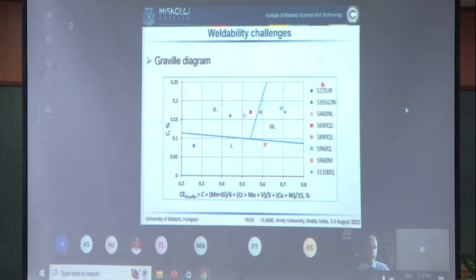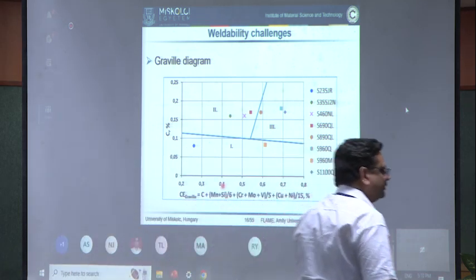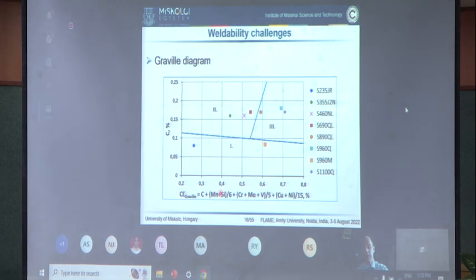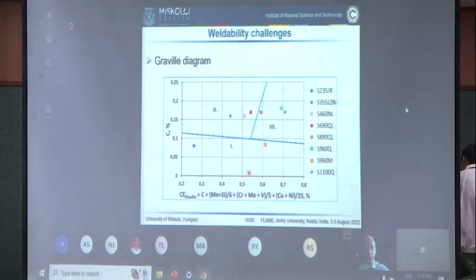In this diagram, my colleagues and I summarized the data of different kinds of base materials based on the base material certificates and the chemical composition, and then we put these materials into this diagram. On the horizontal X axis, you can see the Graville carbon equivalent, which is a little bit different compared to the IIW carbon equivalent. Actually, the difference is the silicon. So according to Graville, the silicon also has an important effect on the cold cracking sensitivity. But even though the carbon equivalent is high, if there is no carbon in the steel, there won't be cold cracking sensitivity. So this diagram clearly demonstrates that the carbon content has the most important role in cold cracking sensitivity and therefore the weldability.